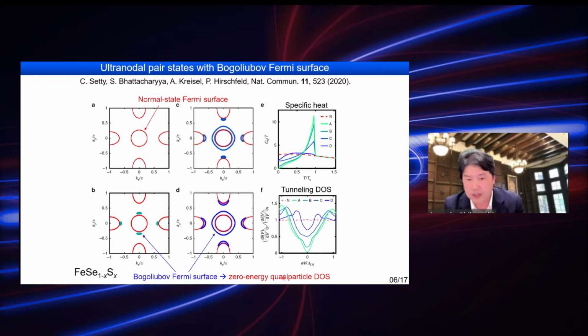And that gives you the zero energy quasi-particle density of states. So if you measure, for example, specific heat, you can find a finite residual C over T. Or if you measure the tunneling density of states, you can find zero bias conductance like this. So that can be tested experimentally.